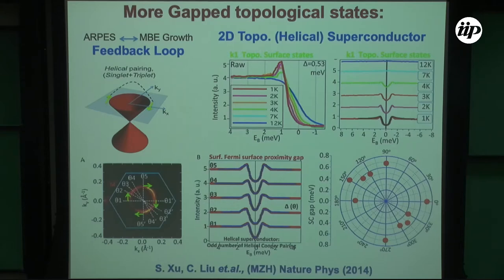Yeah, I mean, it could be. Let's say you realize p plus minus ip, and you have a gap measurement in some space, then that will also be fully gapped, right? P plus ip will give you px squared plus py squared. So when we measure the gap, you cannot tell by gap measurement and anisotropy measurement alone that it's p-wave or s-wave. It's not directly phase sensitive. Yeah, you have to do other things, but I'm saying that.